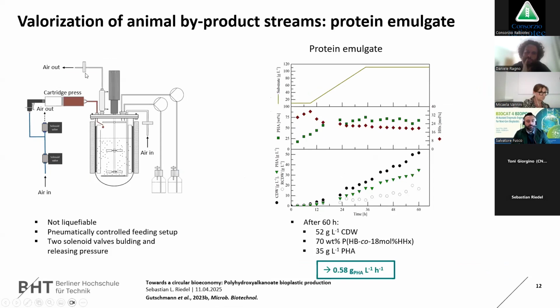Then an interesting feedstock, this is protein emulgate, from producing heparin in the pharma industry. You use swine mucosa, and this material consists of fat and oil. After this extraction, it has a consistency like tomato paste when you feed it, so you cannot use a standard feeding operation. So we developed a cartridge press with different solenoid valves and a computer program, and then we were able to feed this to the bioreactor.